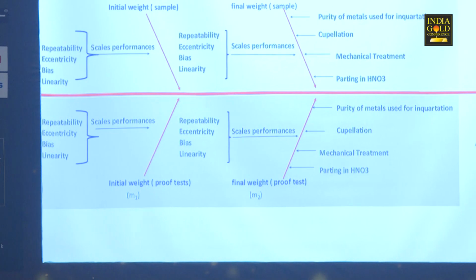Going deeper into the details of the fire assay process, we must consider that the fire assay analysis basically is a ratio between a final weight and an initial weight of a sample, to which we apply a correction based on a variation of the final weight of the proof. So we have an initial weight and the final weight of samples and proofs, and the contribution in this step mainly comes from the performance of the scales that we are using. The parameters that can be considered in this case are the repeatability, the eccentricity, the bias, and the linearity of the scales.